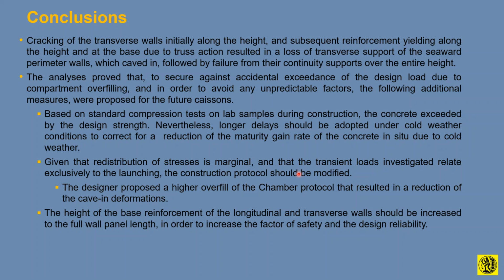one thing that was proposed by the designer was a different protocol for the overfilling of the caisson in order to install it. In fact, in order to revert the inner caving of the chambers, the chamber was filled with higher water level first. There was a differential level of water imposed in the chamber to unbalance, if you like, an anti-force in order to take the external compression forces and remove somehow, as much as possible, the bulging inwards operation of the cantilever because of the presence of this chamber. So the cracking could be alleviated somehow more by the overfilling of the chamber differentially during the flotation and the sinking phase. So this was implemented in all the future caissons, and from then on, there was no other problem.